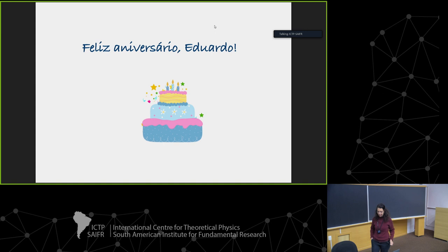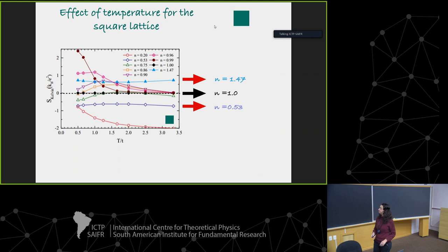Thank you for this very interesting talk and beautiful results. Really a lot of interesting new features discovered here. I have some very specific questions. In the Hubbard model, we know that the Mott gap can open at very high temperatures, but spin correlations associated with antiferromagnetism, even though in 2D they're suppressed, kick in at an energy comparable to the super exchange. In cuprates, you have pseudogap physics at temperatures of the order of hundreds of kelvins, maybe not more than 5% of the Fermi temperature. My impression is that your temperature range is somewhat higher, where magnetic correlations probably don't play such a big role.